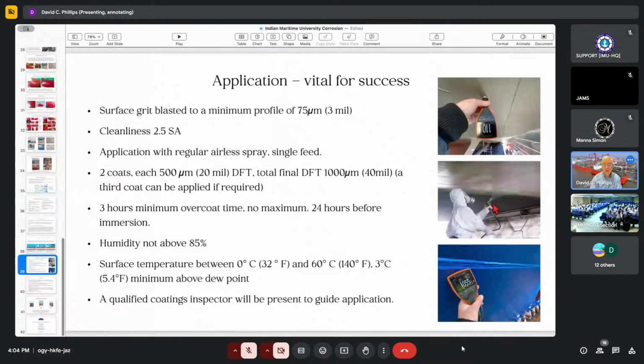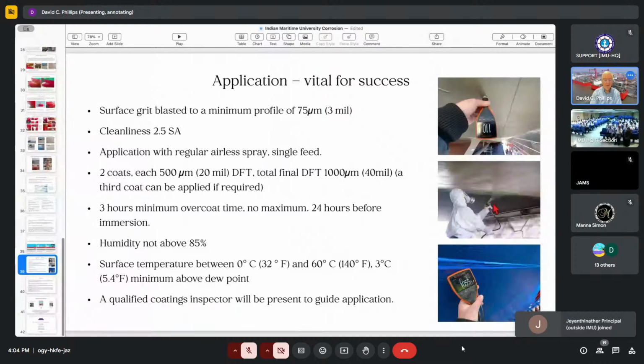You put on the first coat to a dry film thickness of 500 micron, 20 mil. I don't know, do you use micron or do you use mil in India? What's the usual measurement? Metric? Metric. Okay, so 500 microns. The first coat goes on. That's quite thick. That's actually as thick as most coatings are total or thicker. It does not run. It's easy to apply. And then you have a 3-hour wait period. And then you're ready to put on your second coat, which is quite quick.